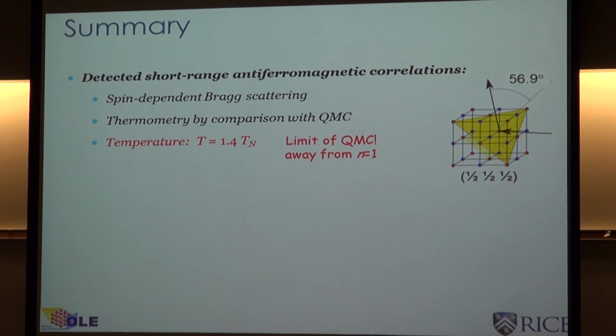So in summary, we've seen short-range magnetic order. We've seen the order has a range here of about 1 or 2 sites. And so what we have to do, obviously, is to get to lower temperatures. We get down to the Néel temperature, that signal goes from being 1.4 to being something of order 1. And so it's really less than a factor of 2.